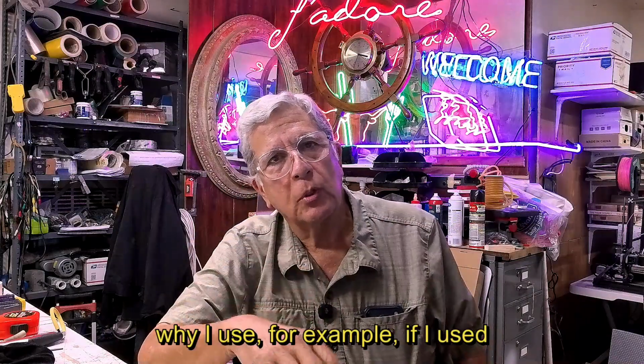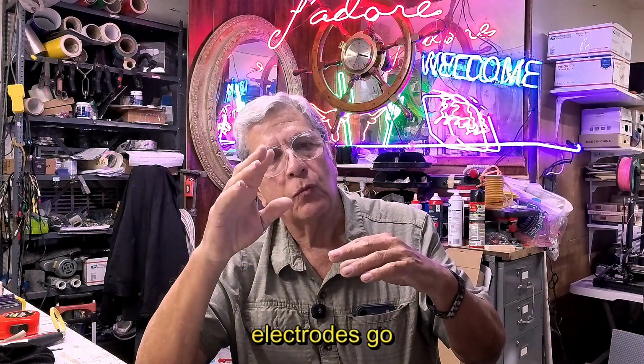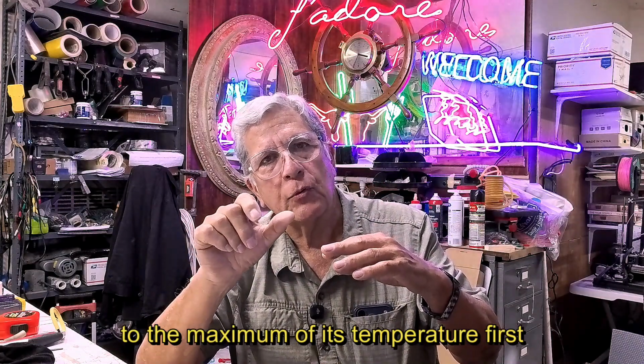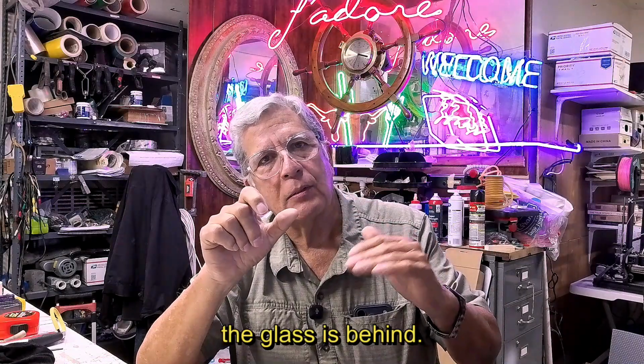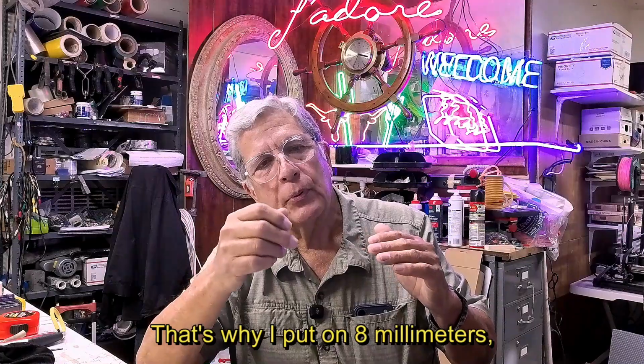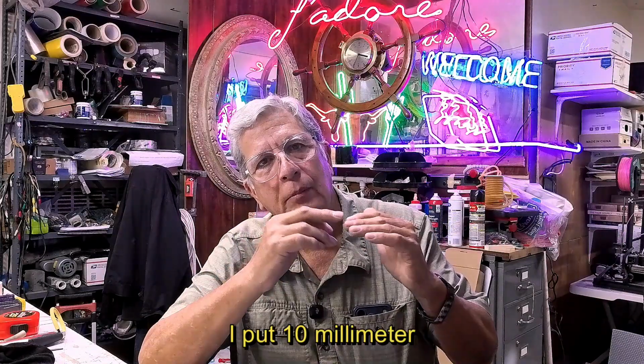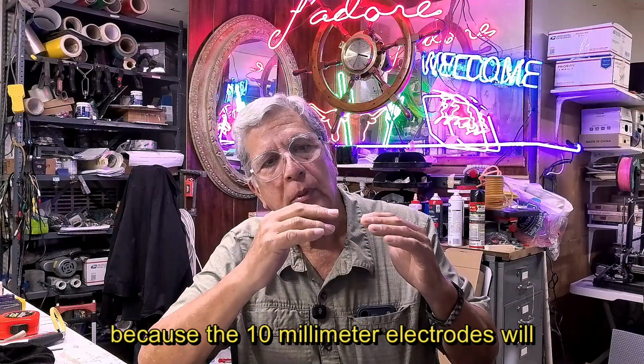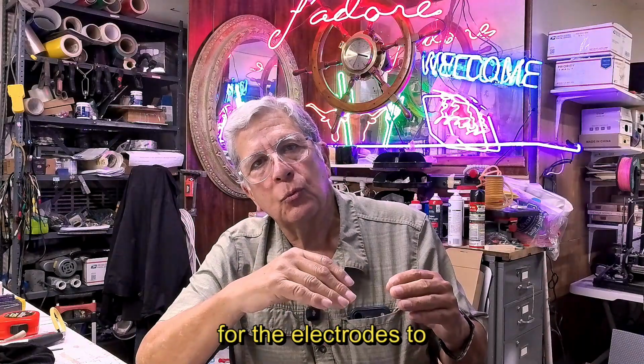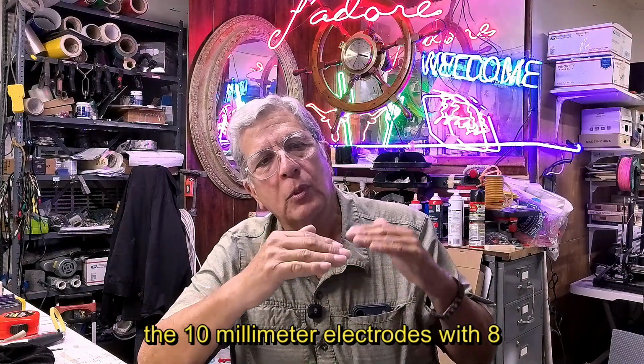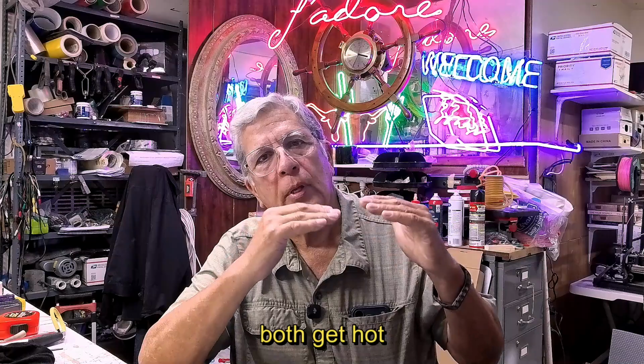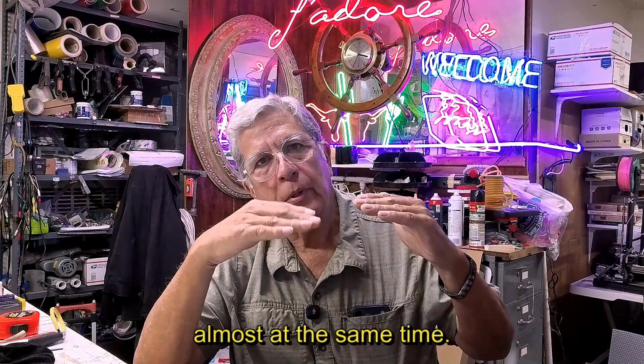So that's why I use, for example, if I used 8 millimeter electrodes on 8 millimeter glass, what happens is the electrodes go to the maximum of its temperature first, and the glass is behind. So that's why on 8 millimeters, I put 10 millimeter electrodes, because the 10 millimeter electrodes will need more time to get completely orange. So the 10 millimeter electrodes with 8 millimeter glass, they both get hot almost at the same time.